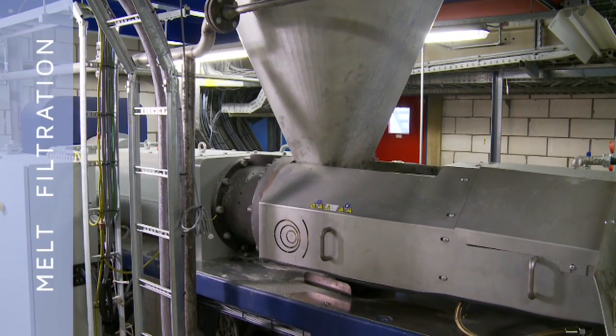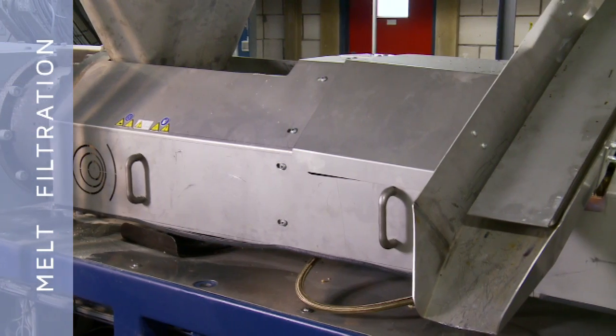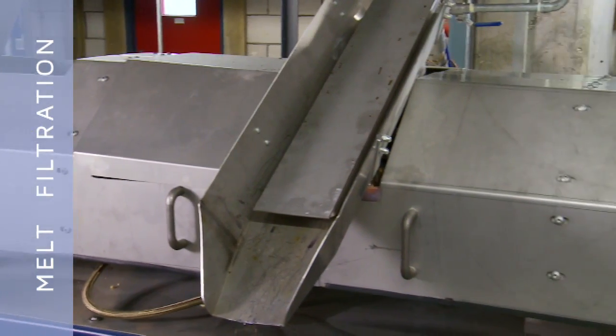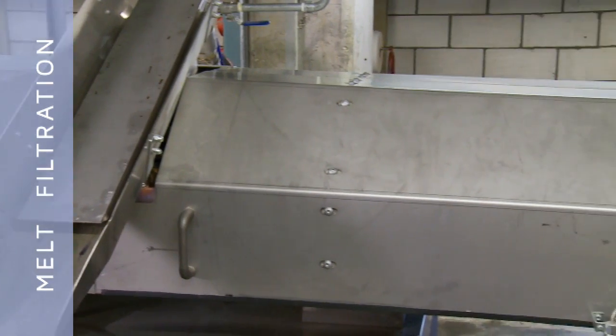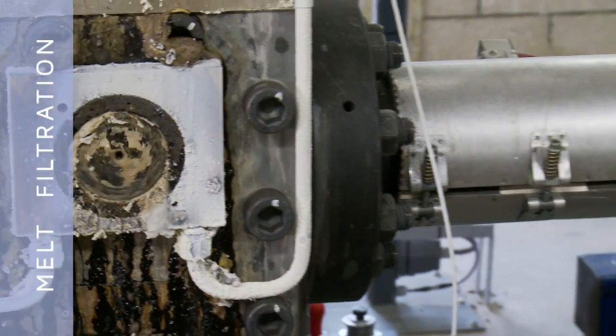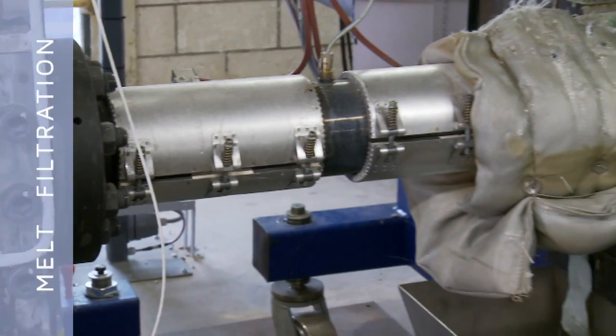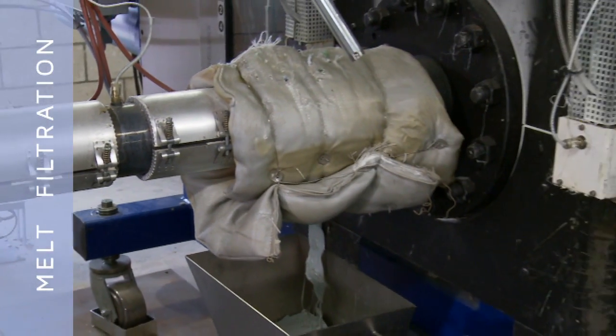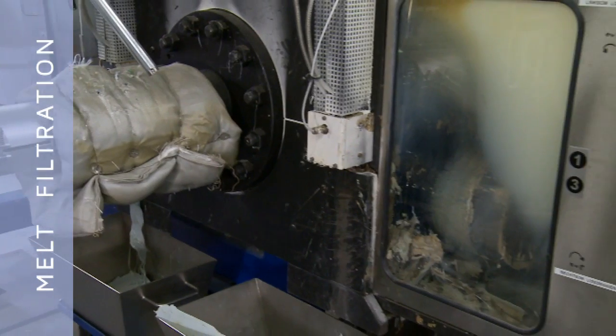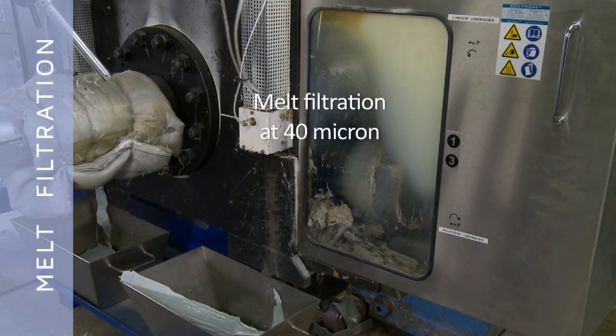Although the flakes are washed at high temperatures by our suppliers, the level of solid contaminants, like sand and aluminium cans, is still too high to make a good quality bottle again. These contaminants are eliminated by pressing the polymer melt through a very fine filter to remove all visual solid contaminants.